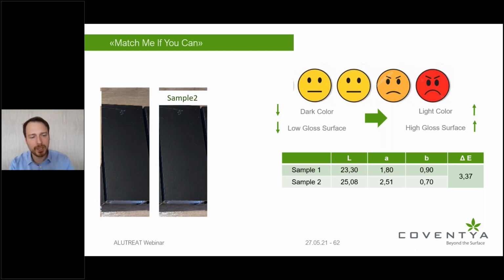So right now we have our basis material that we have adjusted or conditioned with a pretreatment. Then we have grown the right oxide layer on top, which gives us the right template. And by doing these, you can at least say our lab is quite happy. They're not very happy, but at least for black samples, for dark and not very shiny samples, they can assume or anticipate what type of color they're going to get. It's not a guessing game anymore.